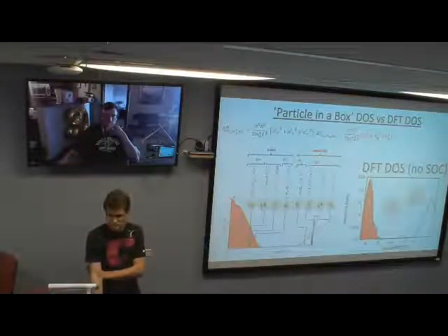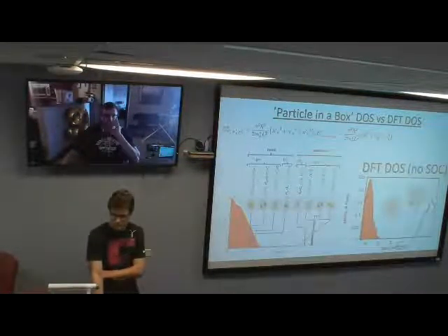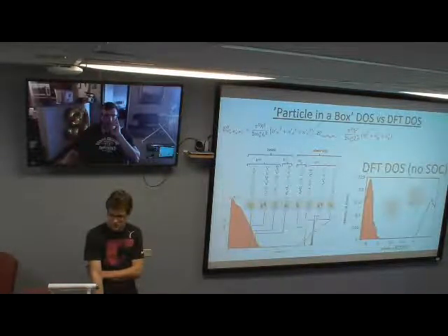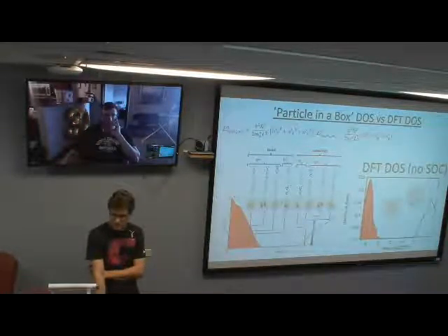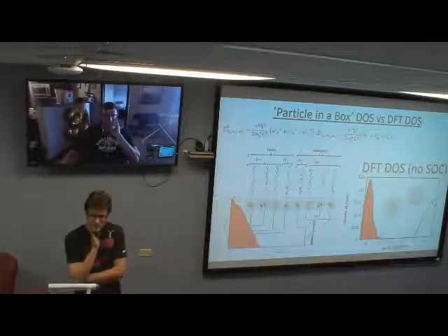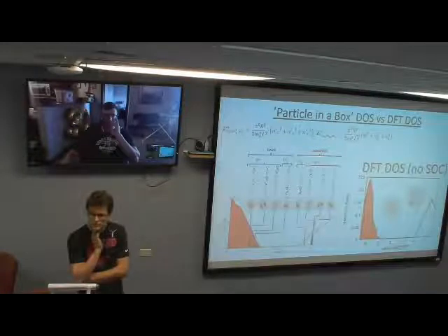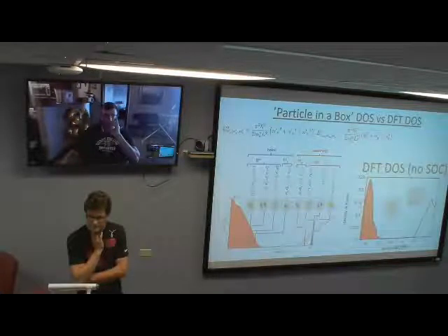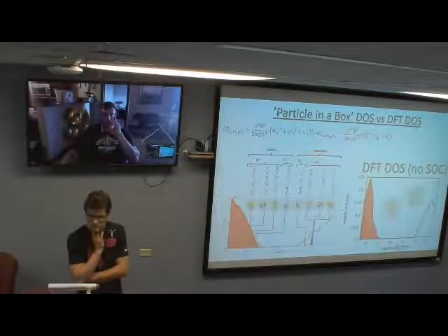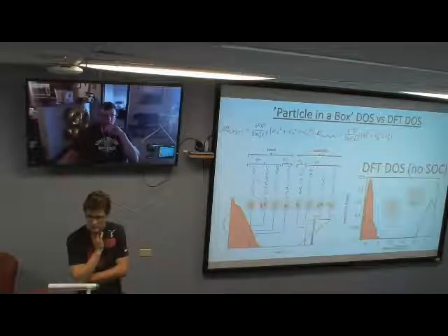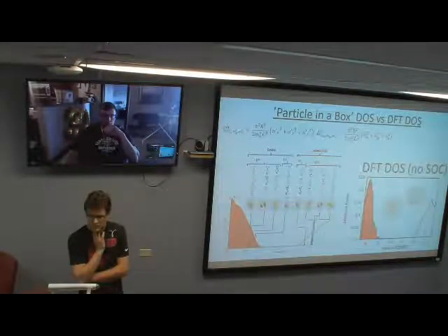Again, quicker, not slower, compared to the infinite box? 5 angstrom is a huge distance. We have examples of the DFT orbitals. But if you put a finite potential, then the shape of the wave function will be like this, depending on the parameter of the height. If you match the depth of the box to the potential of these DFT models, one should get approximately what is seen in DFT calculations. I agree, yes. And 5 angstrom is really a huge distance. Typically, the tails of the wave functions are shorter.